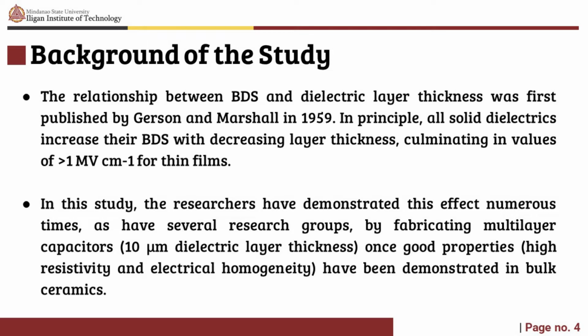The relationship between BDS and dielectric layer thickness was first published by Gerson and Marshall in 1959. In principle, all solid dielectrics increase their BDS with decreasing layer thickness, culminating in values of greater than 1 MV/cm for thin films. In this study, the researchers have demonstrated this effect numerous times, as have several research groups, by fabricating multi-layer capacitors with 10 micrometer dielectric layer thickness.